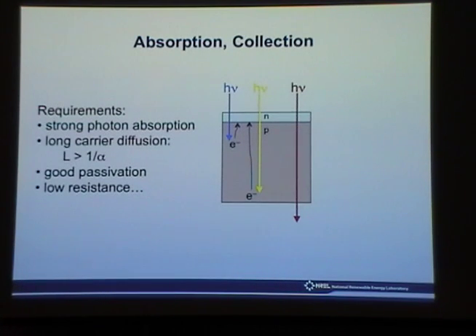So you're actually sacrificing the high current in the high current layer. Yeah. So in this way, you are still losing some of the photons that are coming in. Right, but the broader point is that a 2-junction device with gallium arsenide and gallium indium phosphide is nowhere near the optimal configuration of band gaps. So if you're forced to use those band gaps, for other considerations I'll come to in a second, then you do what you can to current match, because if you don't current match, your efficiency is going to go down. So the better way is to try to engineer a structure that has exactly the band gaps that you want, and then you can make the cells optically thick and you sacrifice nothing. The only time you'd have to thin it is, I mean, pretty much every cell we've ever made is away from optimal. And so then you would thin it in order to make it current match.